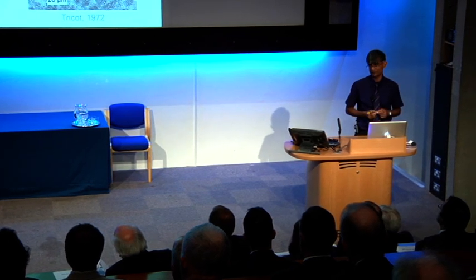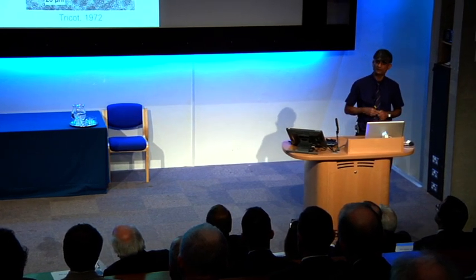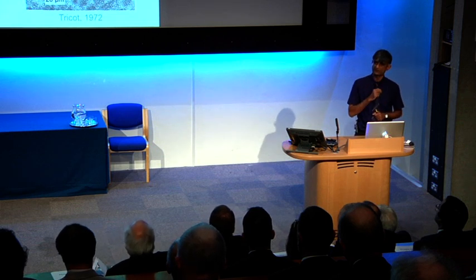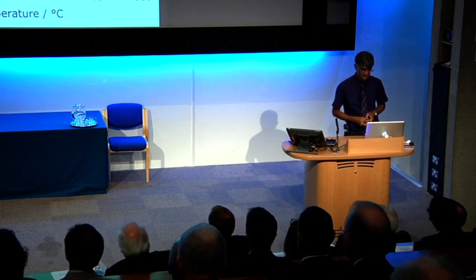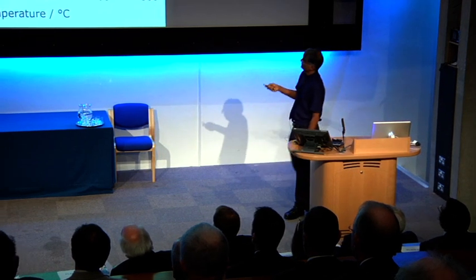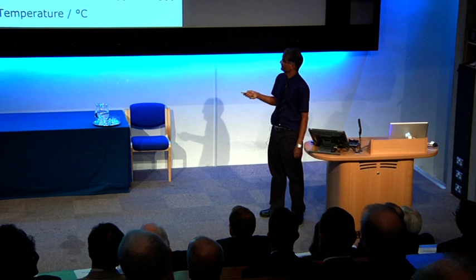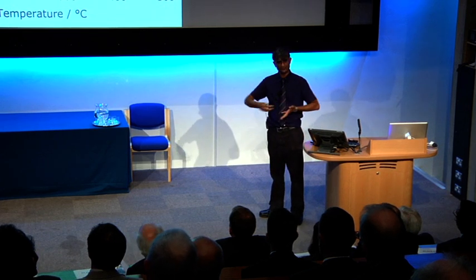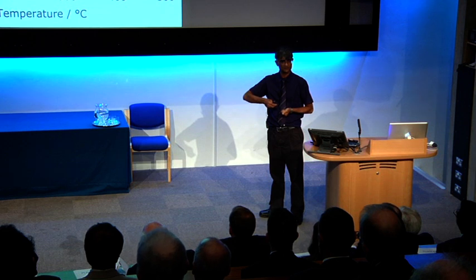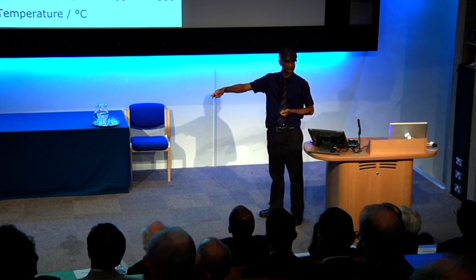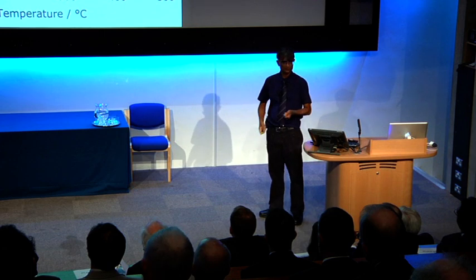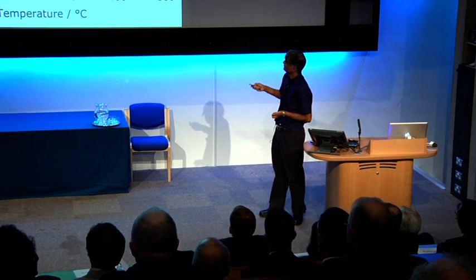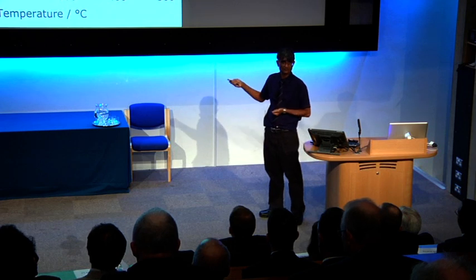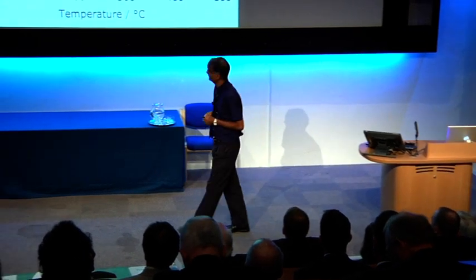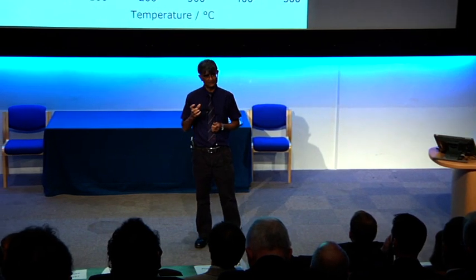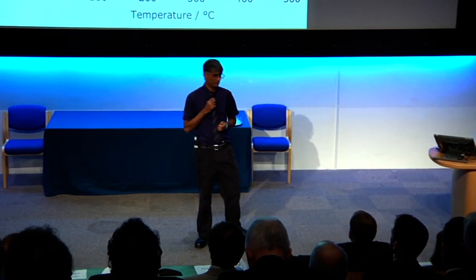Hydrogen is going to get into the steel. Perhaps we can stop it from doing damage by trapping it at sites where it wants to be. And this is the normal response from a bearing steel, that you've got a lot of diffusible hydrogen. So this is basically a spectrum where you take a piece of steel, charge it with hydrogen, and allow the hydrogen to evolve as a function of temperature. If your peak is at a low temperature, then it's diffusible hydrogen. If it is trapped at strong traps, then it evolves at a higher temperature. Now, how can we design a steel in which there will be traps for hydrogen?